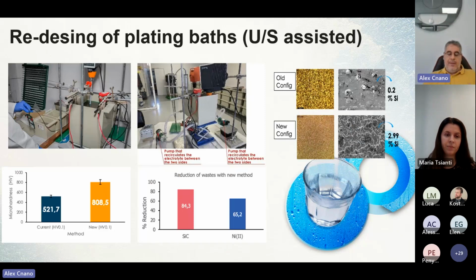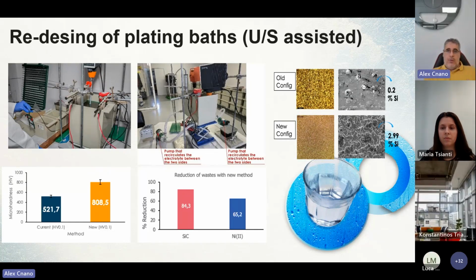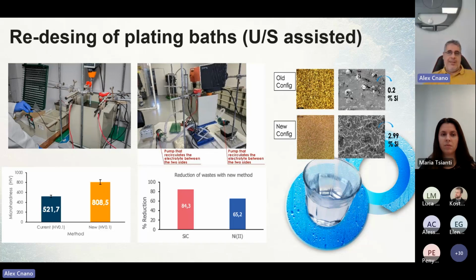Another example is the redesign of plating baths, especially when it comes to composite plating, where we do have particles inside the bath solution. This is a very big change for the bath. So there is a very big need to keep nanoparticles always in suspension. The level of the dispersion that we will achieve in the plating bath is the level of the dispersion that we will have for these nanoparticles in the final coating. So excellent dispersion in the electrolyte means excellent coatings.